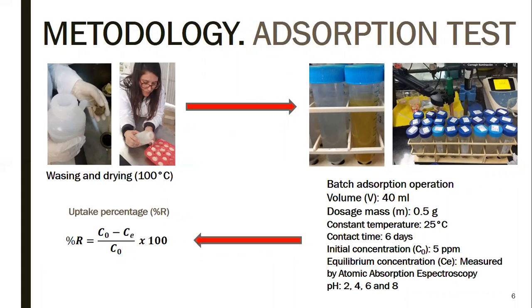After geopolymerization, samples were washed and dried for subsequent adsorption tests, which were performed by batch adsorption operation at a constant temperature of 25 Celsius degrees for a period of 6 days, in a volume of 40 milliliters and dosage mass of 0.5 grams at an initial concentration of 5 parts per million, varying pH at 2, 4, 6, and 8. The uptake percentage was calculated by the following formula: initial concentration minus equilibrium concentration, divided by initial concentration. The result times 100.